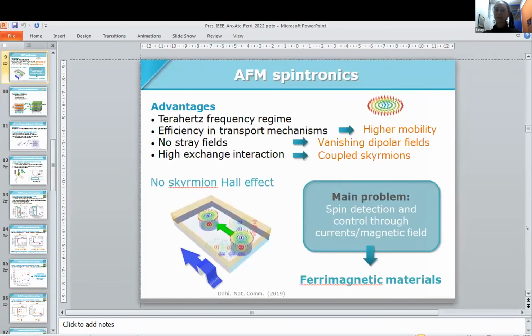So this is where the spintronics based on antiferromagnetic systems arises. There are several advantages. First, when we are dealing with antiferromagnetism, you can go to the terahertz frequency regime. The second one is that you have a higher efficiency for transport mechanisms. So if we translate this for skyrmions, this means that you will have a higher mobility for skyrmions if they are propagating in an antiferromagnetic host. Since it's an antiferromagnetic material, you have no stray fields, meaning no dipolar field or a really small dipolar field, and this will mean that there will be less interaction from one skyrmion to the neighboring skyrmions, which is something that we want to achieve.